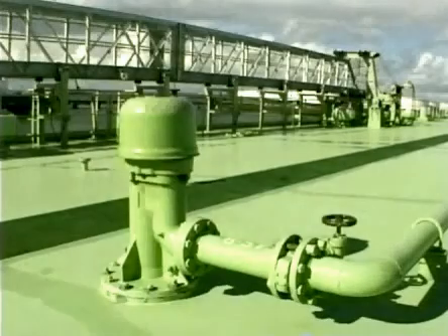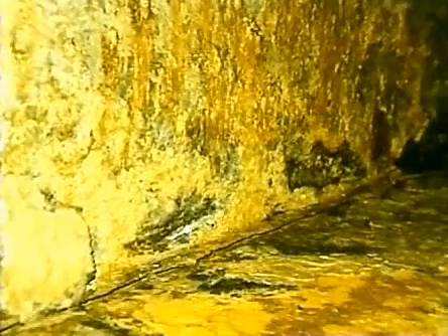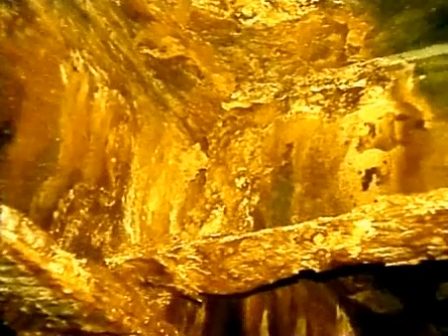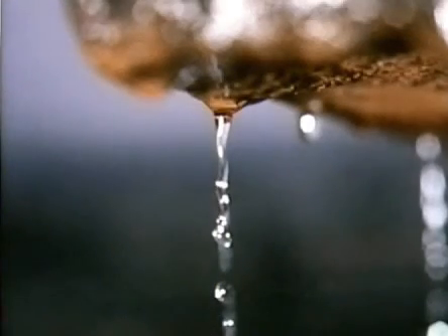The cleaning operation performed between cargo and ballast modes may consist of crude oil washing of the tank or salt water washing before loading the ballast. The combination of crude oil and water ballast makes tanks suffer from corrosion to a much greater degree than pure cargo tanks, because the washing medium removes the protective oil film from the steel surface. Where salt water washing is routinely done, this destroys the protective film and washes away loose scale, thus exposing fresh steel and allowing renewed corrosion to take place.